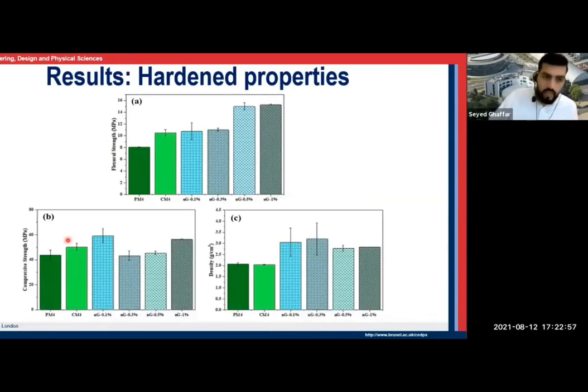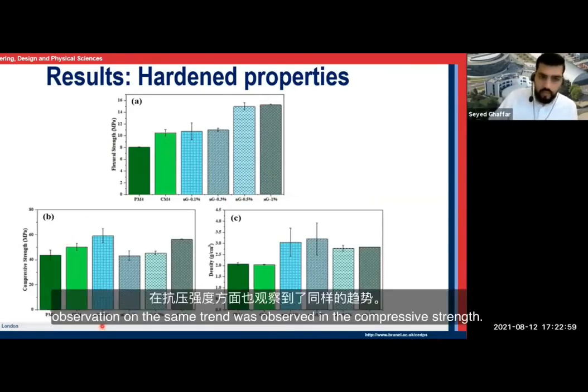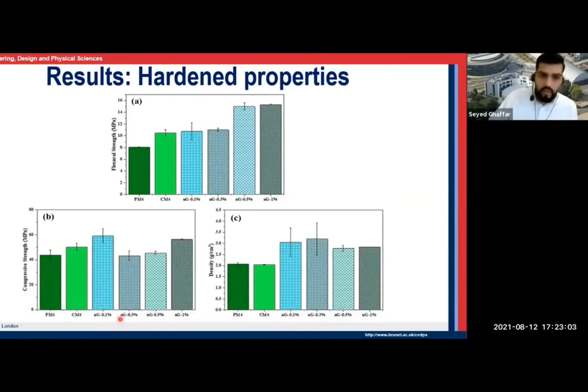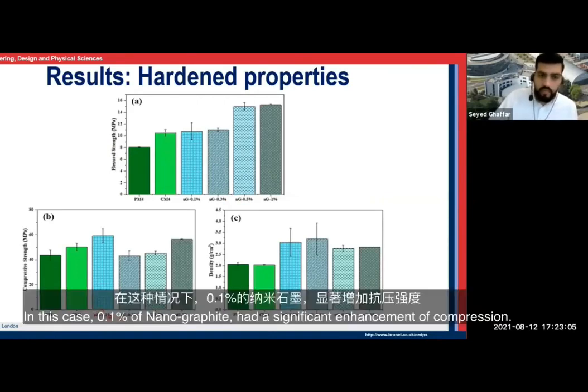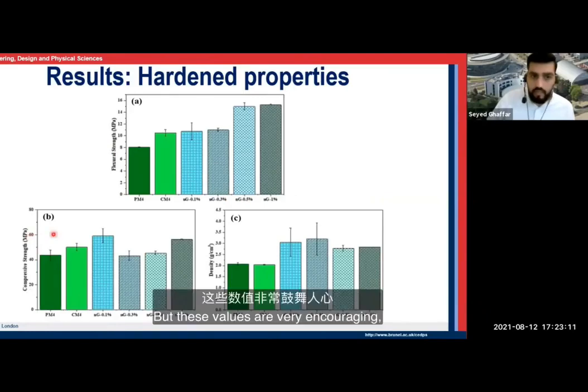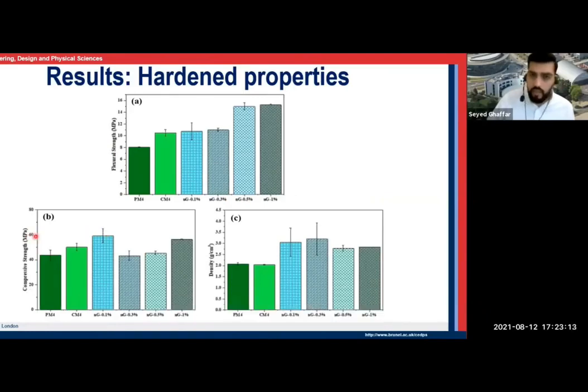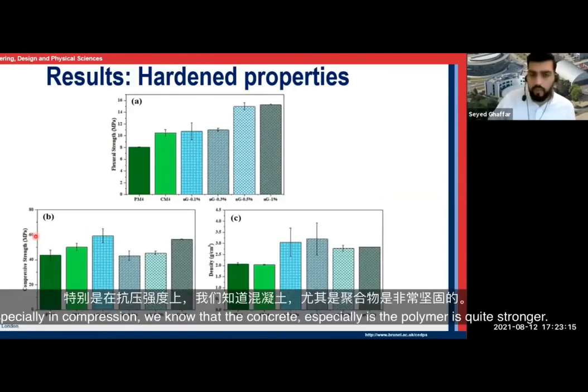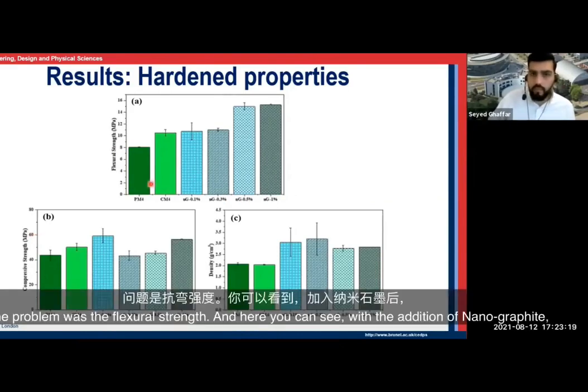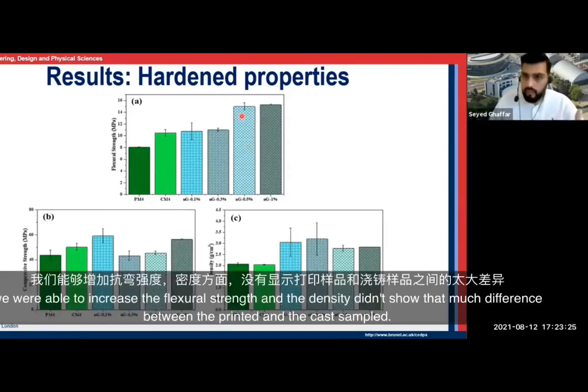So the same trend was observed in the compressive strength, where in this case, 0.1% of nanographite had a significant enhancement of compression. But these values are very encouraging, especially in compression. We know that the concrete, especially geopolymer, is quite strong, but the problem was the flexural strength. And here you can see with the addition of nanographite, you're able to increase the flexural strength.